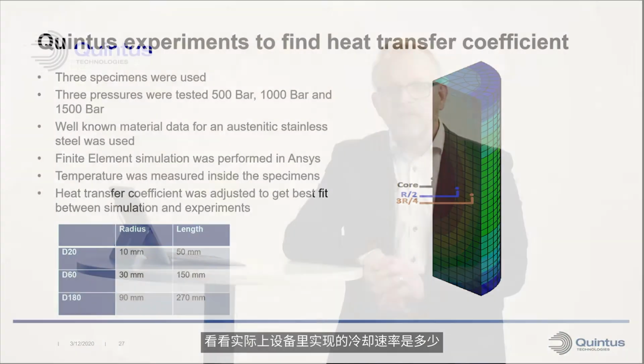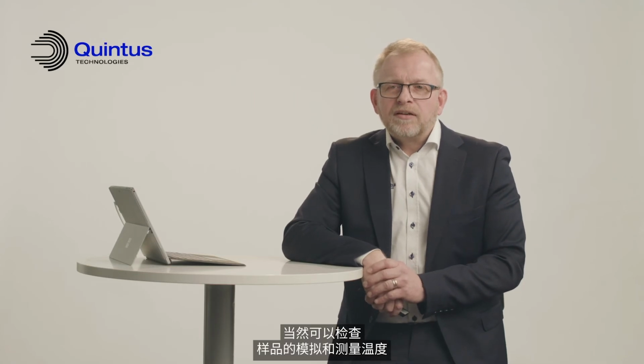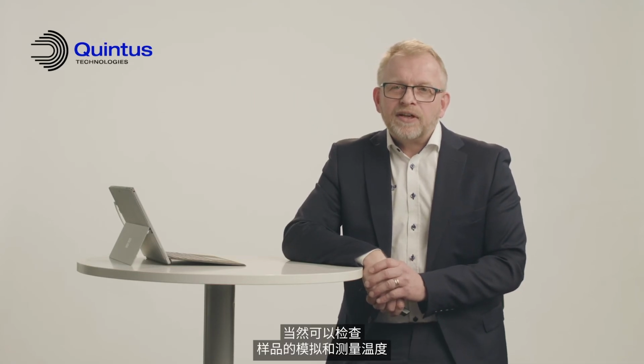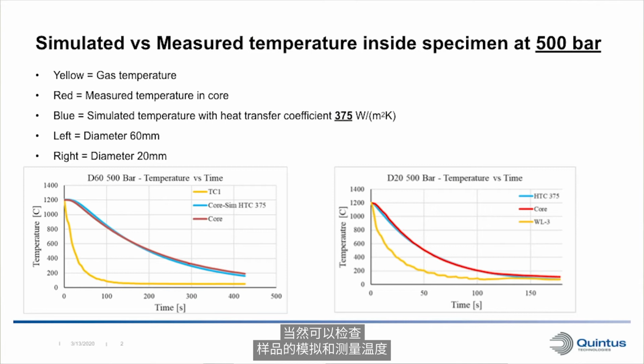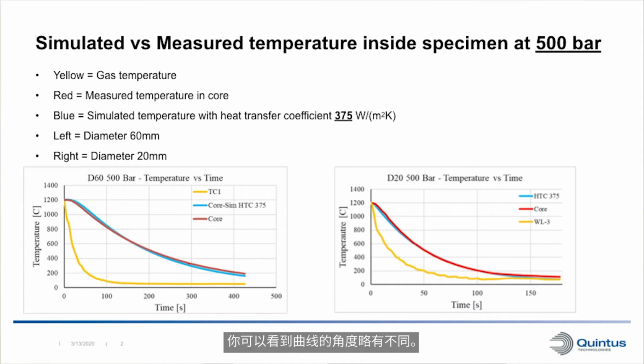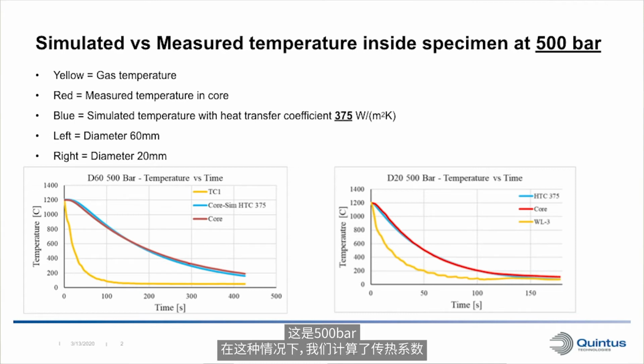And check this at different pressures also to see what is the cooling rate that's actually achieved in the equipment. The simulated and measured temperature in specimens can be checked, of course, and in this case it's the diameter 60 and on the right the diameter 20 millimeter parts, and you can see that the curves have slightly different angles. This is at 500 bars. And in this case, we calculated the heat transfer coefficient, alpha, to be 375.